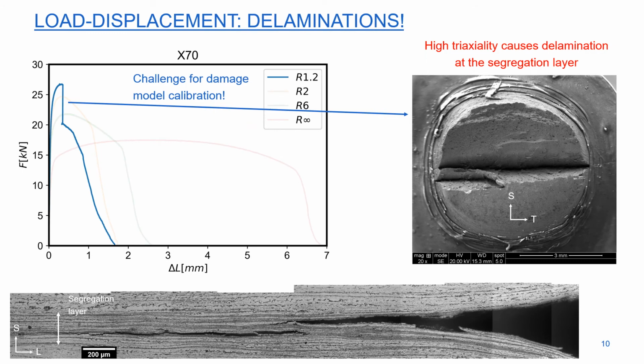A more detailed microstructural investigation shows that this load drop is caused by the occurrence of delamination in the segregation layer. A cut in the transversal plane shows how deep the delamination runs and the position of the crack with respect to the segregation layer. Since a ductile damage model cannot describe brittle behavior, the occurrence of a delamination is a considerable challenge with respect to calibrating the damage model.